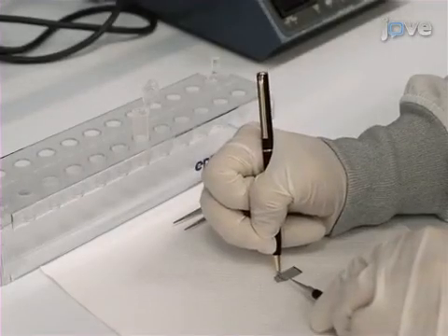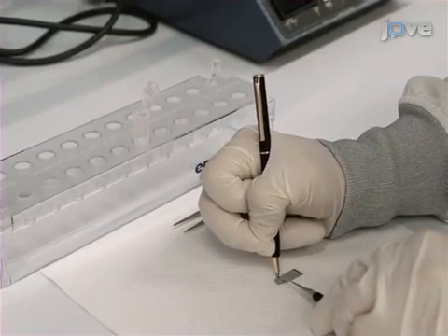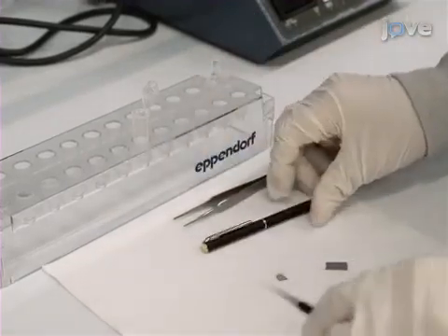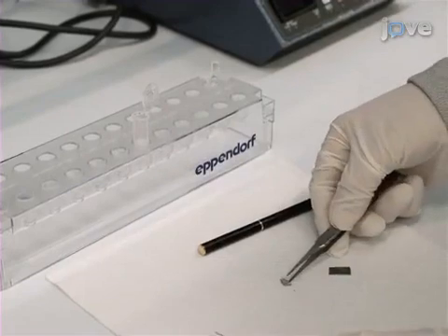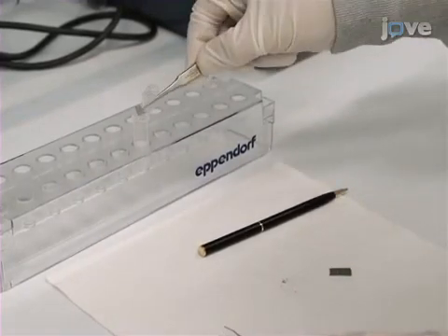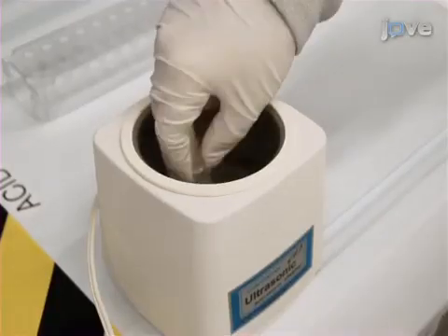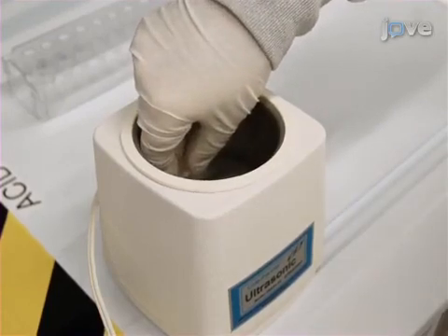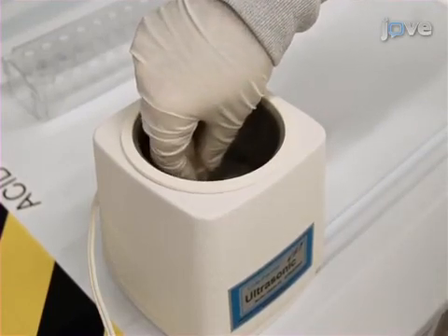To begin, cleave a small piece of the as-grown gallium nitride nanowires on a 111 silicon substrate and place it into a small vial with 1 milliliter of isopropanol. Sonicate the vial for 30 seconds in order to remove the nanowires from their anchoring substrate.